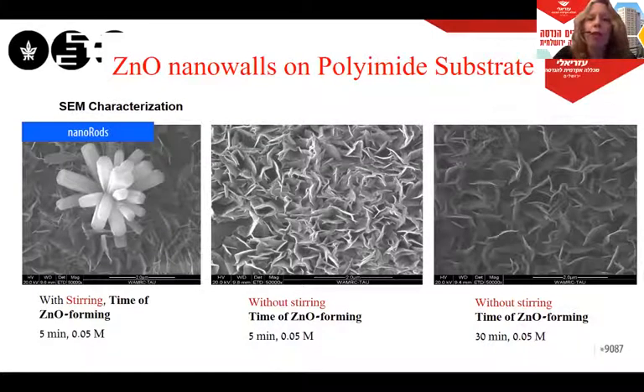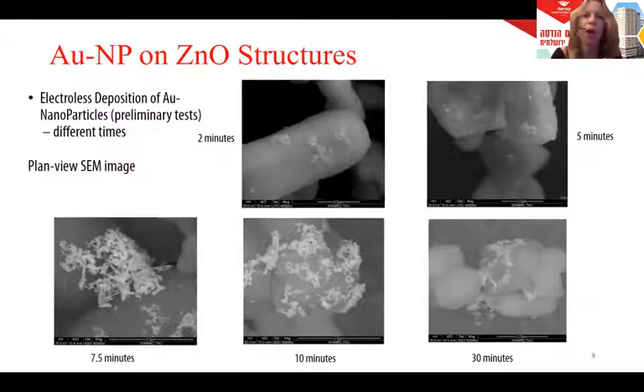The next step that we wanted to do is to deposit gold nanoparticles. However, we did it in parallel. So we did a gold nanoparticle electroless deposition before we managed to do the ZnO nanowalls. So here you can see deposition of gold nanoparticles, electroless gold deposition for different times, from 2 minutes to 30 minutes. But the ZnO is not a nanowall at all, it's hardly nanorods, some kind of nanostructure.